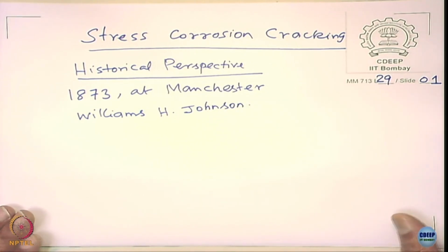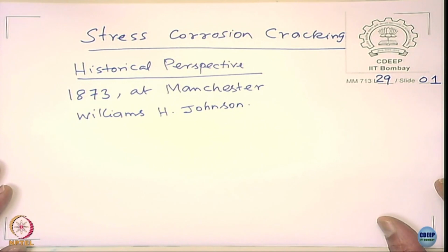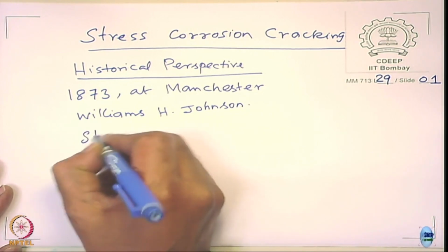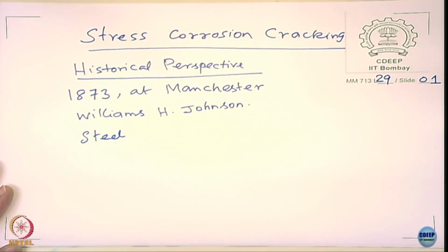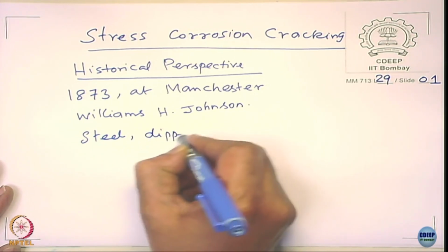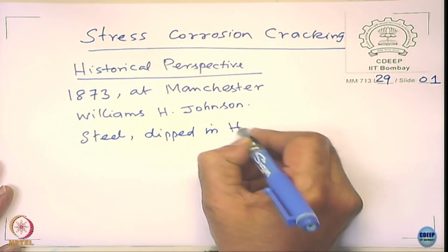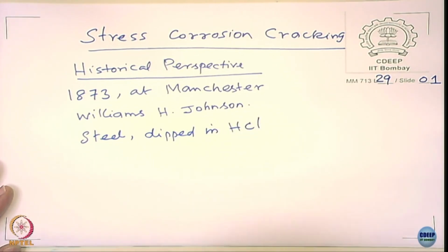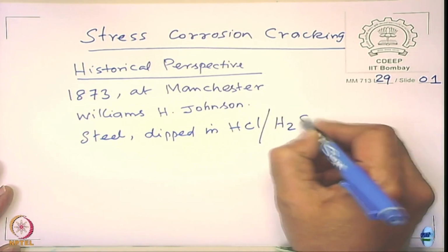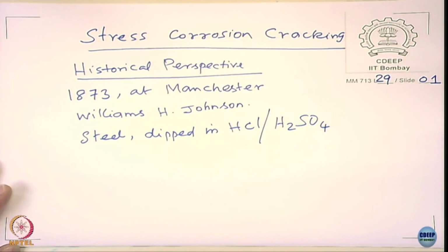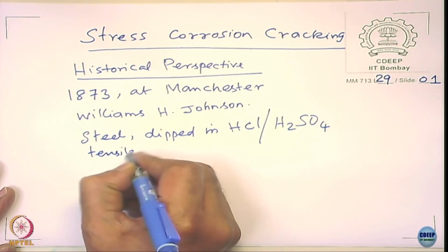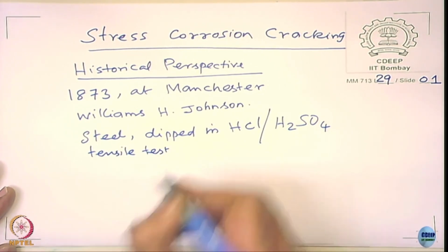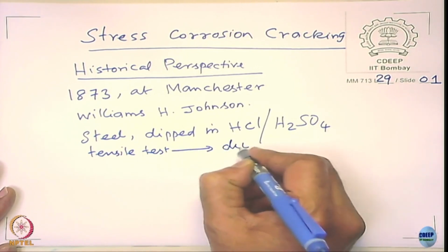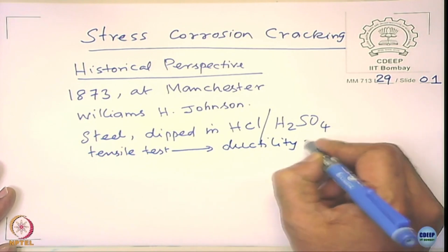did a very interesting, curious experiment. What he did was he took steel and dipped it in hydrochloric acid and also in sulfuric acid, both the acids. He just dipped it, and then he carried out a tensile test. He found that ductility reduced significantly.